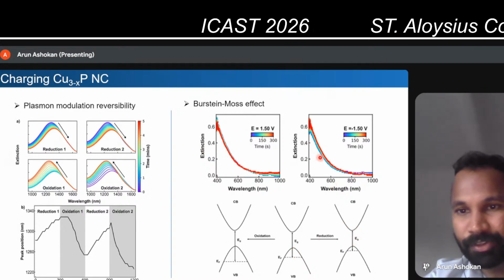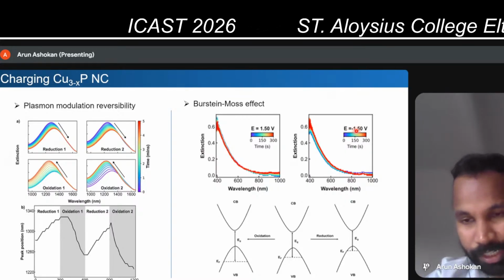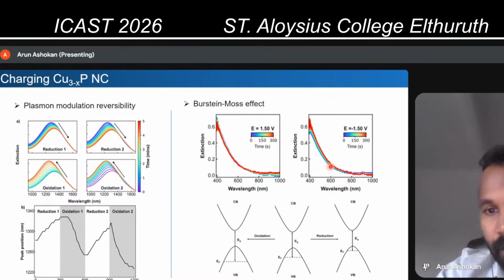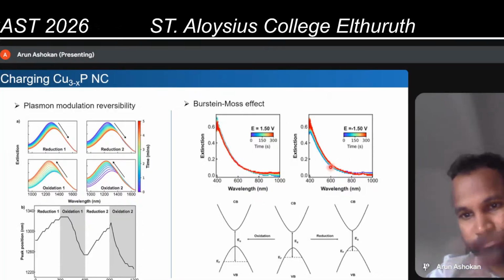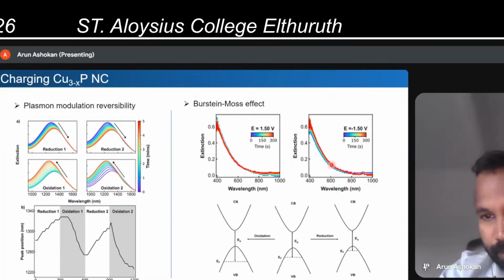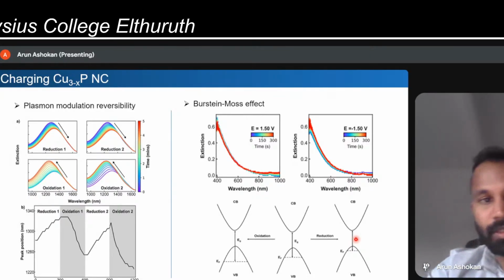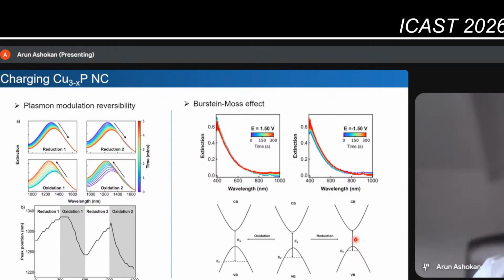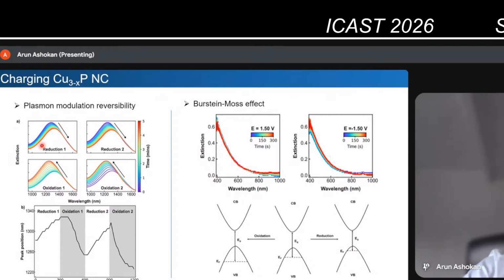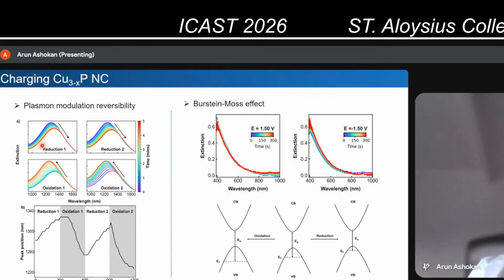So you see that when you apply minus 1.5, which is a cathodic potential or a reducing potential, you can see the absorption redshifts. This is because of the reduction in band gap. So to sum up, we have shown how we can charge semiconductor nanocrystals and modulate the plasmon frequency of these nanocrystals by electrochemistry and simultaneously detect using spectroscopy. So spectroelectrochemistry has been used here to do that.